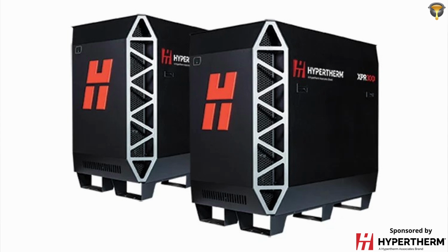So it's likely going to require some of the gates, especially in the biscuit area, where you have a lot thicker gates, and especially if they want to scrap or remove the biscuit first, real close to the big round biscuit, you can go to an XPR system, XPR 300, or an XPR 460. It'll give you enough amperage to sever the 40 millimeter, or even some larger than that. But we're not encountering those yet. Usually, again, between 2 and 40 millimeters is where we're at now in the industry.